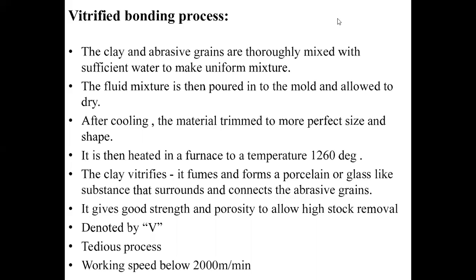The clay is vitrified in the furnace to form a porcelain or glass-like substance that surrounds and connects the abrasive grains. This vitrified bond looks like a transparent kind of thing. A glass-like mixture is formed at the end when you heat to this temperature, hold for some time and cool down. This vitrified bond is denoted by V, and it gives very good strength and porosity to allow high stock removal.